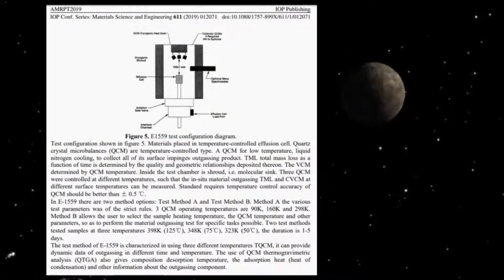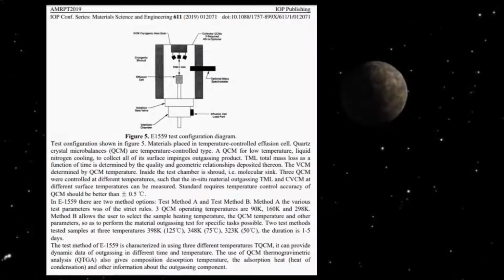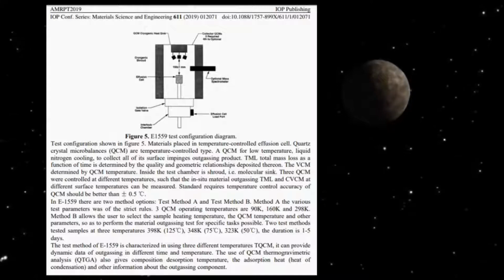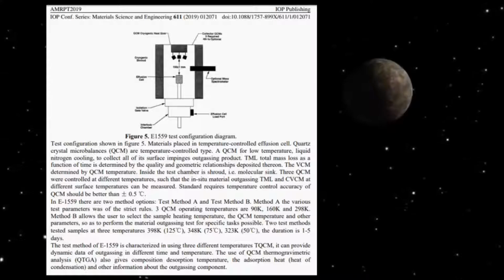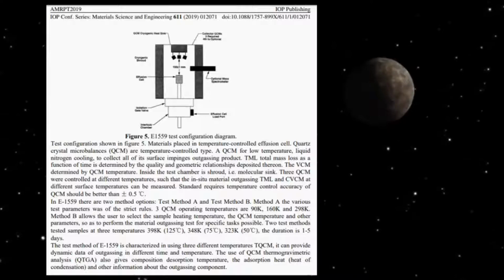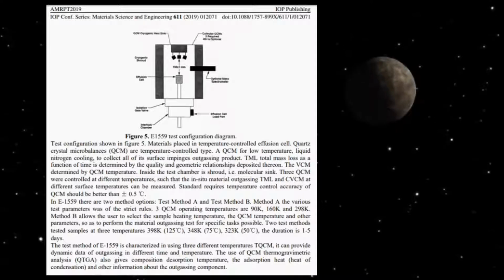Test configuration is shown in Figure 5. Materials are placed in a temperature-controlled effusion cell. Quartz crystal microbalances are temperature-controlled. A QCM at low temperature, with liquid nitrogen cooling, collects all outgassing products impinging on its surface. TML, total mass loss as a function of time, is determined by the mass deposited and the geometric relationships. The CVCM is determined by the QCM temperature. Inside the test chamber is a shroud, i.e. a molecular sink. Three QCMs were controlled at different temperatures, so that the in-situ material outgassing TML and CVCM at different surface temperatures can be measured.